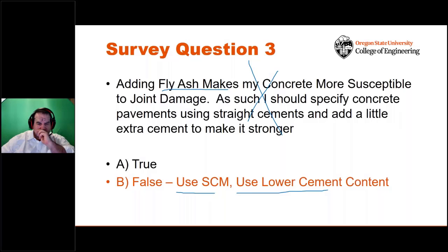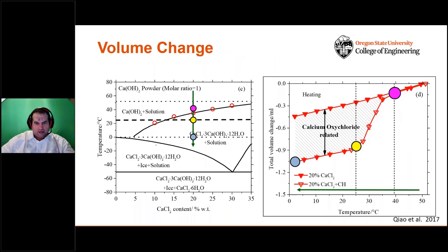Right, again, the other thing I want to do, and this is just that phase diagram again, it's drawn a little bit differently, it's just taken out of a paper, but the whole idea is if we move over here to our right-hand side, if we start out at a high temperature and we drop the temperature of a sample inside of a calcium chloride solution, what we notice is we see a small reduction here. This is just due to coefficient of thermal expansion. And then right about when we get to minus 35 degrees, we see a huge volume change. That huge volume change is because the calcium oxychloride is forming, right?